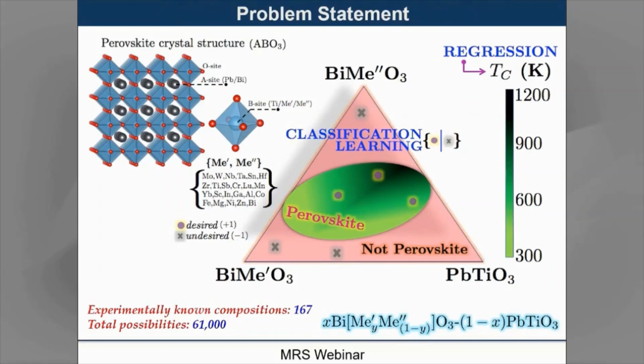So as shown in this triangle, we were interested in a pseudo-ternary phase diagram, and our goal was to identify the chemistry that can go into this ME prime, ME double prime, and also the exact composition X and Y, such that the final ceramic is a solid solution that will have the desired perovskite crystal structure, and the crystal structure is also schematically shown here. In addition, the perovskite should also have a very high ferroelectric Curie temperature, right?